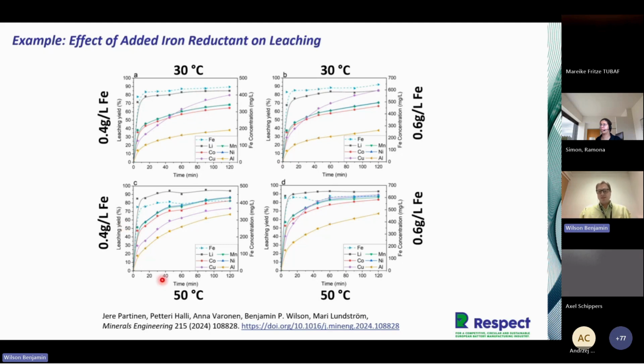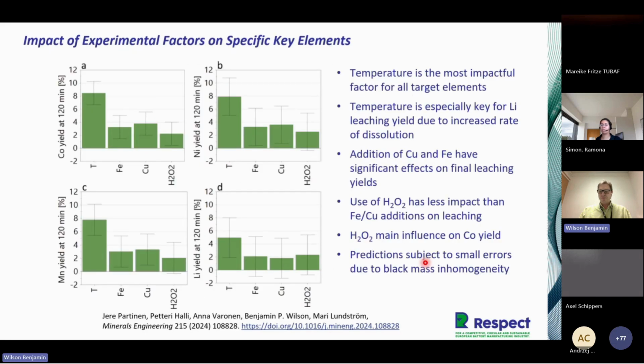But as you can see, once again, once we increase the temperature to 50 degrees, there's an increase in the leaching yield or recovery of the metals into the pregnant leach solution that start to reach more appreciable levels up towards 90%, the targets that we have there. So that was just a quick snapshot of the data. Of course, we had a lot more data if we think about the table of experiments that was listed on one of the previous slides.